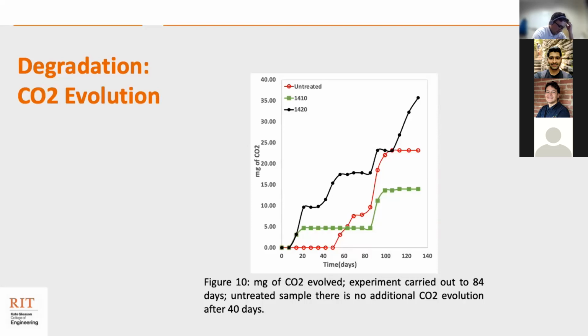The CO2 evolution test was carried out for 130 days, and the red line, or the untreated sample, doesn't evolve any CO2 up to 56 days, which is nearly 2 months, which means the process of degradation doesn't start until month 2. This is called the lag phase of degradation, and the entire reason we wanted to plasma treat these samples is to reduce this lag phase. In contrast, the plasma treated samples start to degrade and release CO2 after 14 to 21 days in soil.